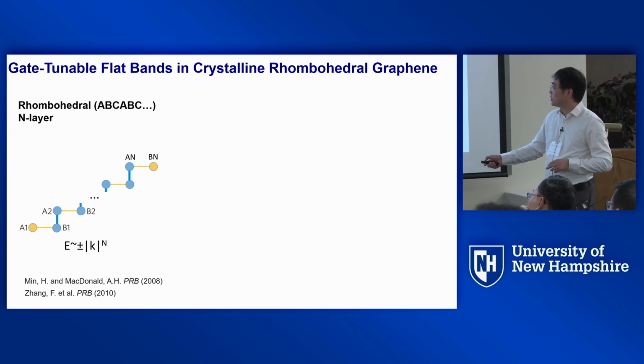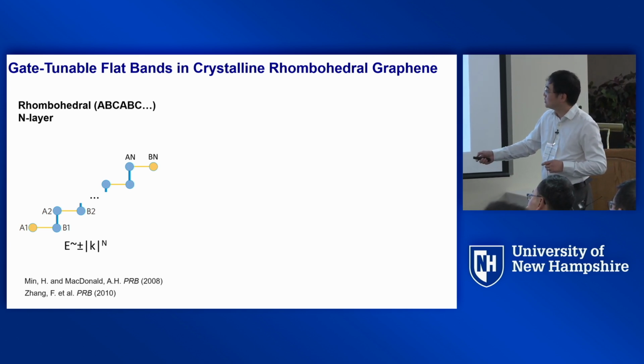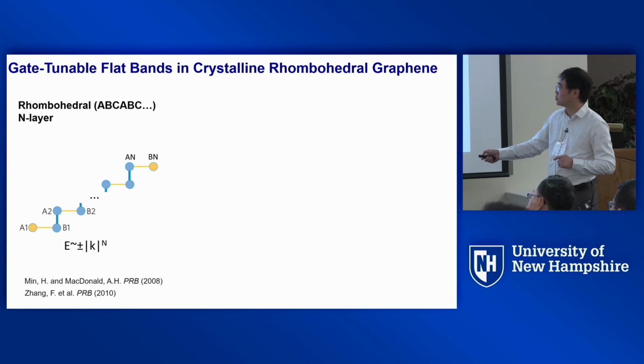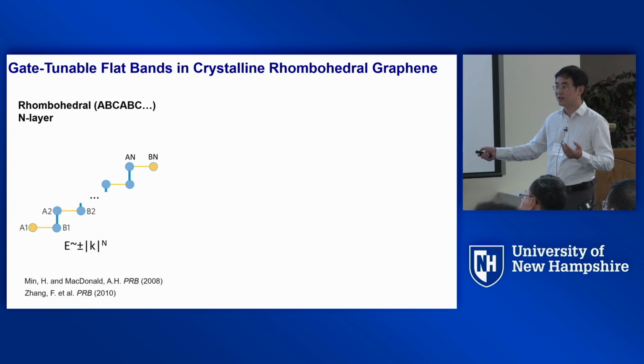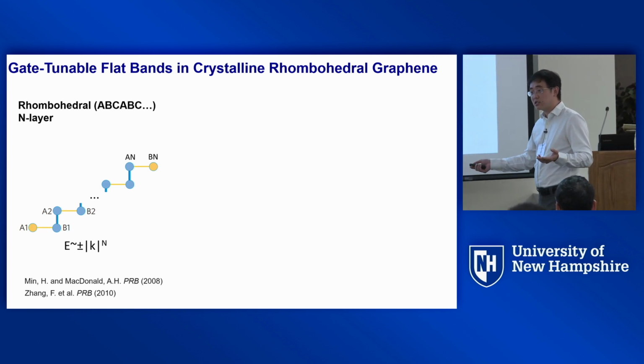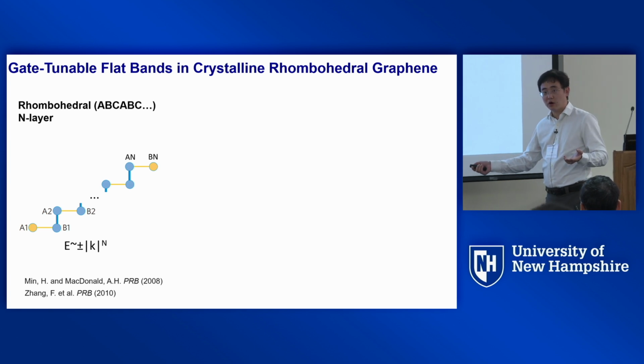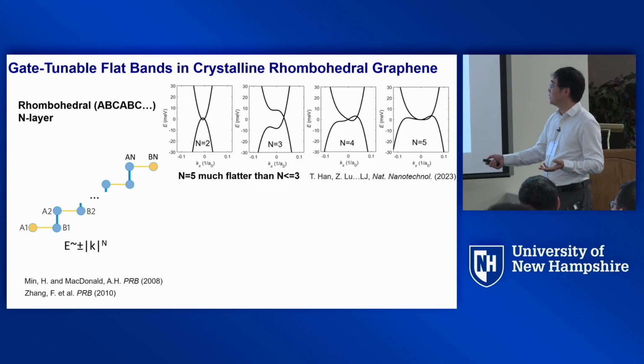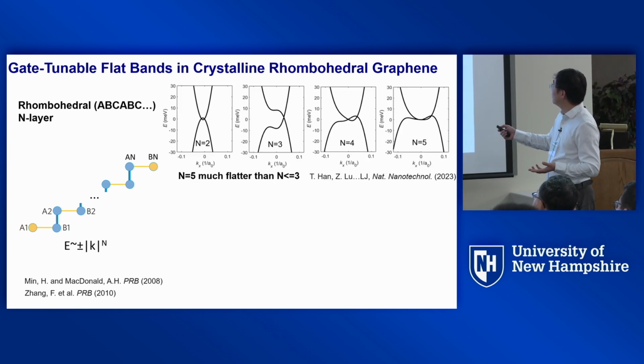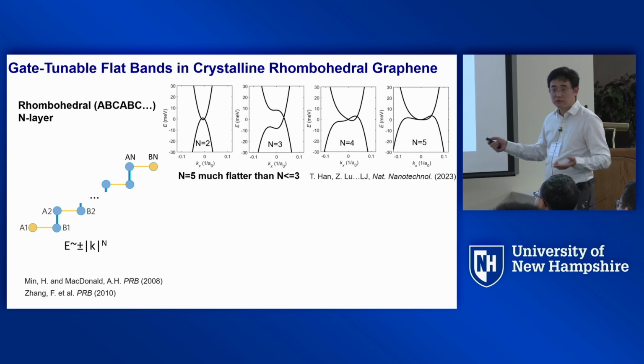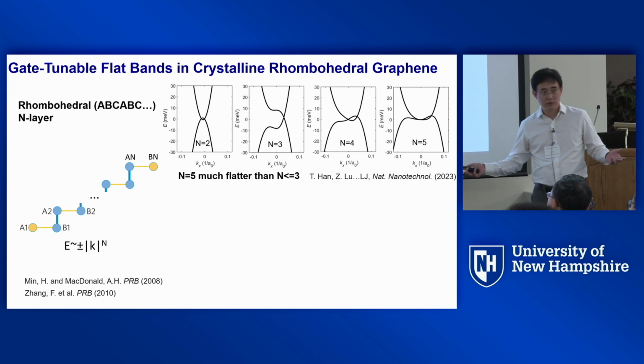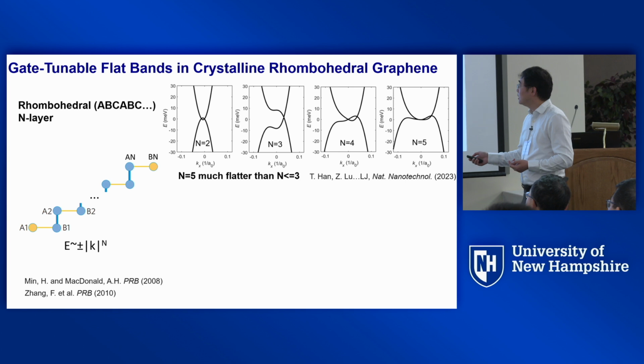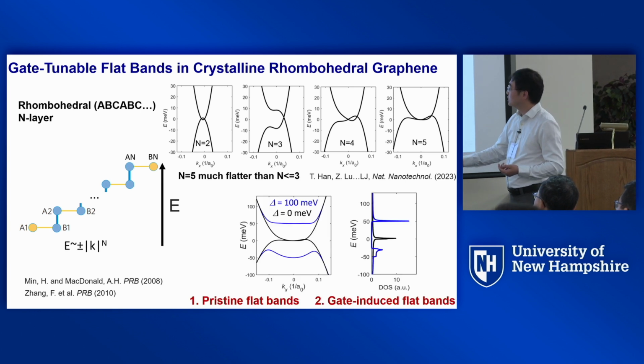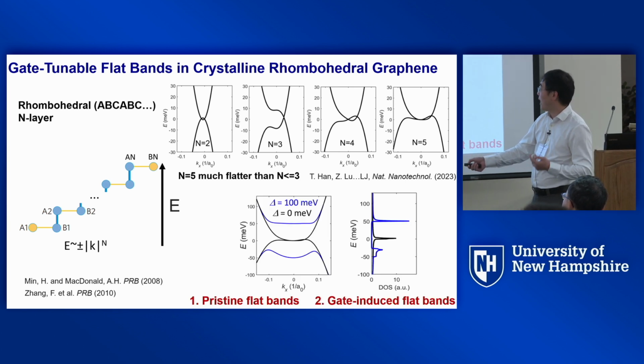And they also give you this very funny dispersion relation where energy is proportional to momentum to the nth order, where n is the layer number. As you can imagine, if it's a monolayer, it's just a linear Dirac. If you crank up the layer number, very quickly, you get more and more flat band for free. There's no moire. There's no twisting.